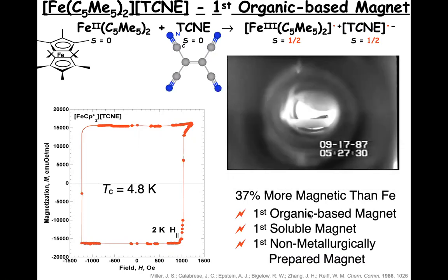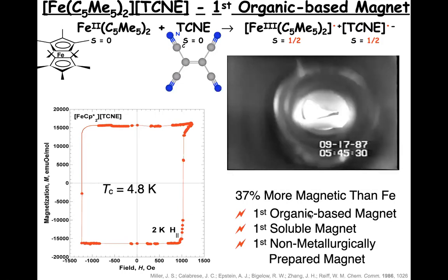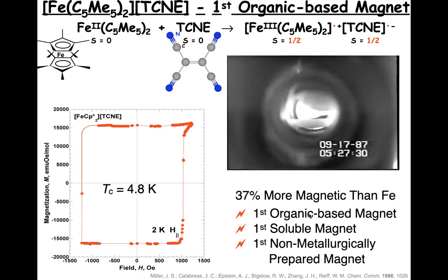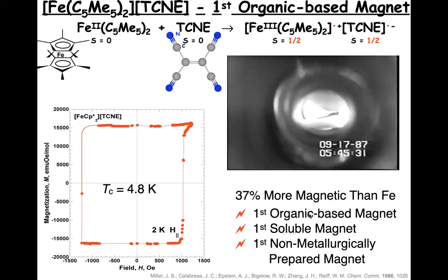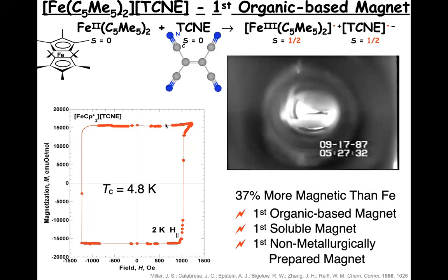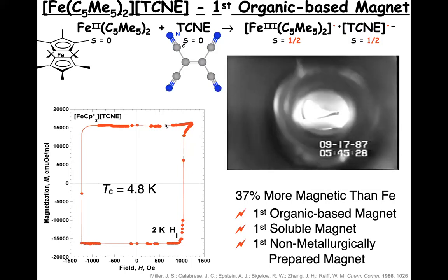It's got a spin in the p orbital on the TCNE radical anion. We've done a lot of controlled experiments by replacing that anion with species that are different, with no spin on it, and it does not magnetically order. It's also the first magnet you can dissolve and remove the solvent and still be a magnet. And you do not have to use high temperature metallurgical processing to make it. The magnetization illustrated on top over here indicates that it is 37% more magnetic than iron metal is on an iron basis or a mole basis. So it's a very interesting magnetic material indicating you can make organic-based magnetic materials.